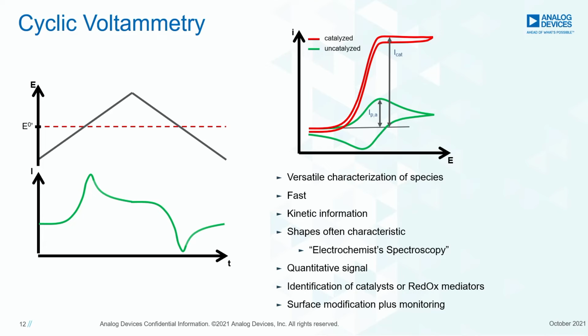and that is very nice, because this is a very versatile technique to characterize species. The peak position, the potentials, so the shape of the whole CV is usually very characteristic for certain species, right? Sometimes it was called, or in the past it was called, the electrochemist's spectroscopy before impedance spectroscopy became very popular. You can get kinetic information, it's very fast, you can get a quantitative signal, so you can use it also for electroanalysis, and you can, for example, identify catalysts or redox mediators, or make surface modifications at the same time while you're monitoring it.